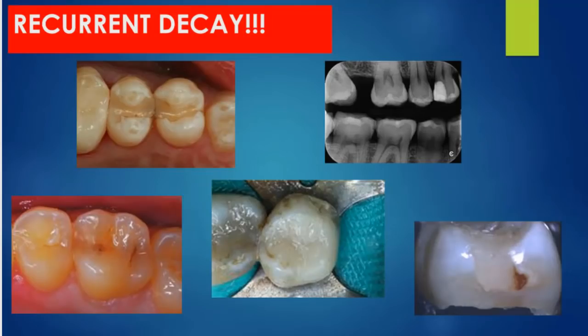Let's move on. Let's talk about what poor performance in any of the 5 areas that we just talked about is going to lead to. It's going to lead to recurrent decay. What does recurrent decay look like around a Class 2 composite? Typically it looks like this. It's breakdown at the cavo-surface margin, usually somewhere within the proximal box, starts off as micro leakage and then manifests itself as recurrent decay, as you see here.